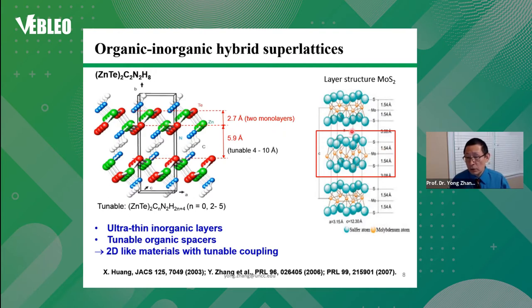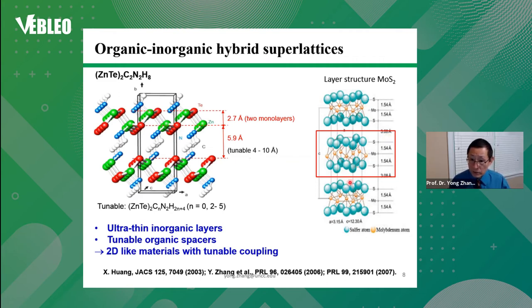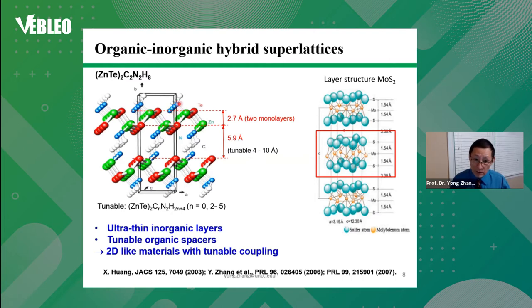There's some similarity to so-called layered materials like molybdenum disulfide, where people study monolayers. However, for those layered structures, properties are very sensitive to the number of layers and you cannot really control the coupling between layers. For this hybrid, we have about the same thickness of each layer, but we can use the organic molecule to tune the coupling between layers, and that doesn't change much no matter how many layers you stack. So this is a nice approach to have stacked two-dimensional structures.